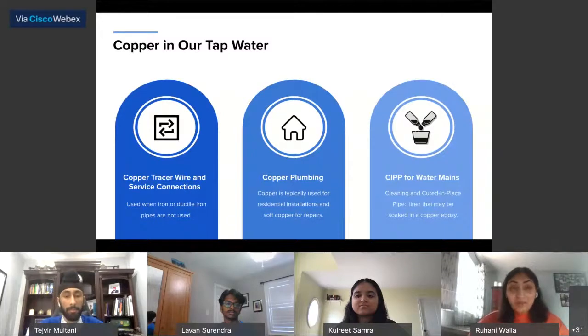Upon further research, we found that the city started a water main structural lining initiative in January of 2015. So they used cleaning and cured in-place pipes, an acronym for that is CIPP, to line the inside of water mains to prevent breaks from happening. The liner is soaked in a combination of resin and epoxy. Further research on this found that resin and epoxy can contain copper.